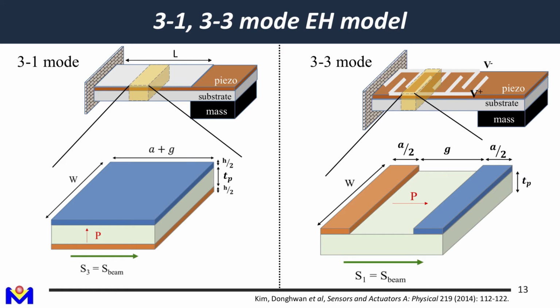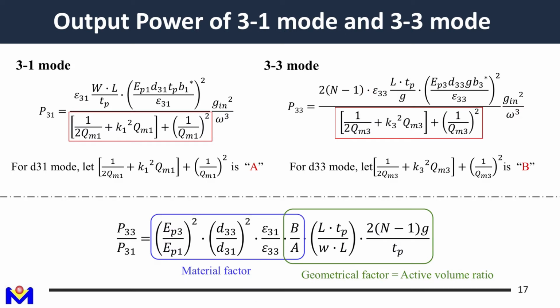So in the end, we can say the power generated from the 3-1 or 3-3 microcantilever beam is inversely proportional to the Young's modulus, proportional to the piezoelectric constant, and inversely proportional to the dielectric constant. And also in the geometry factor, for 3-3 mode it is proportional to the gap between interdigitated electrodes, and for 3-1 mode it is proportional to tp, the thickness of the piezoelectric layer.